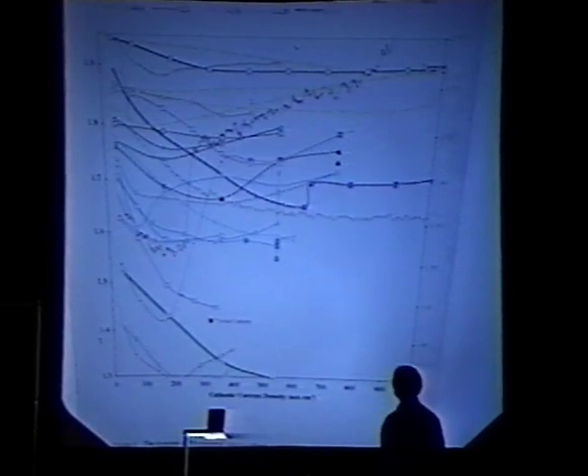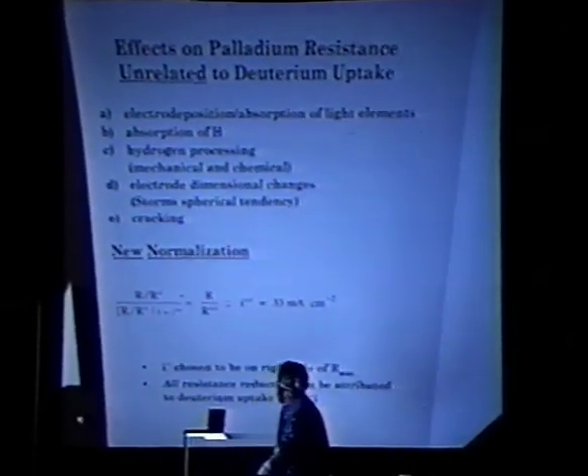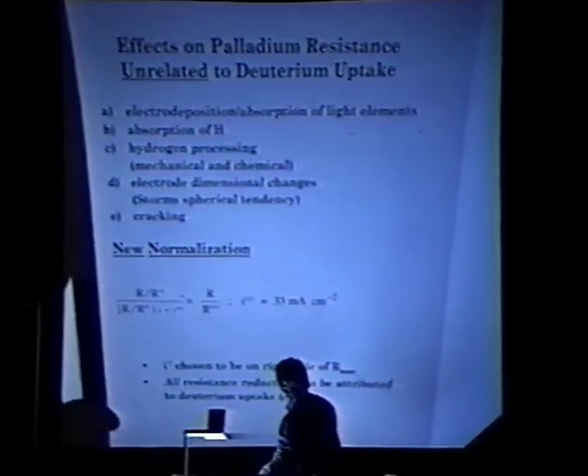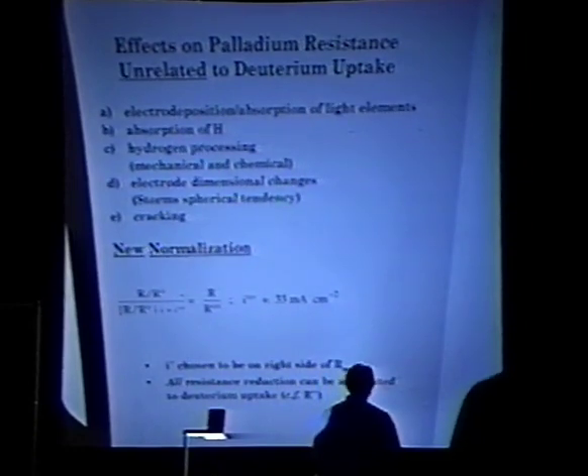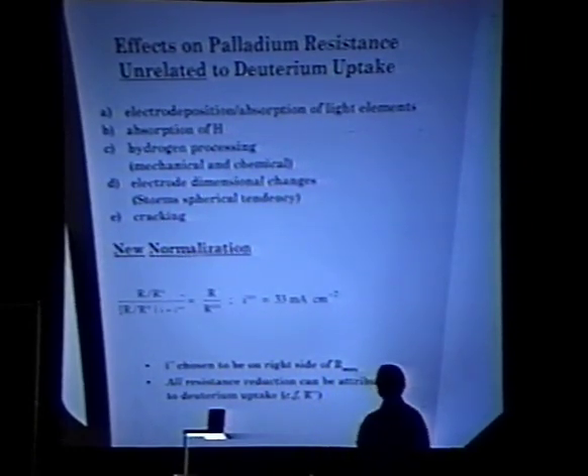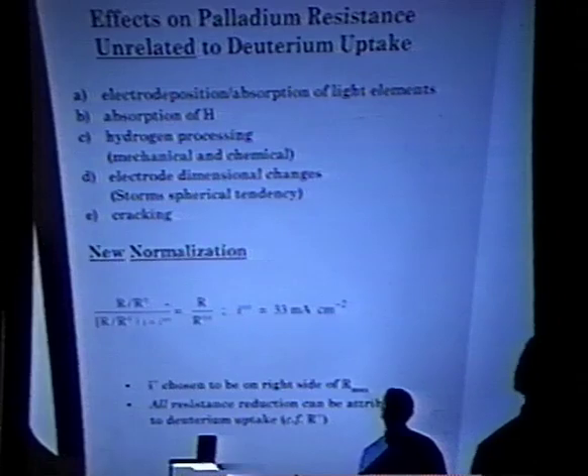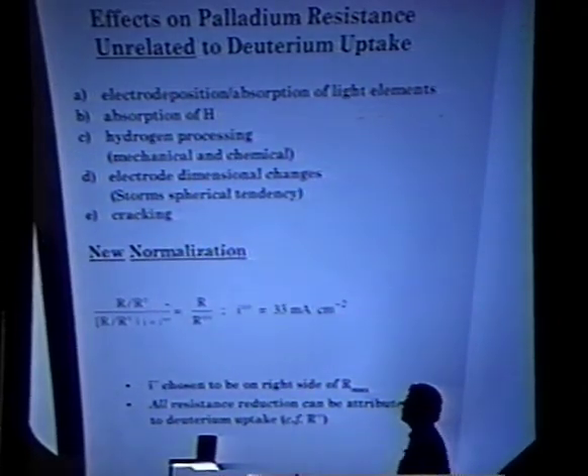There is a trend of a sort that the excess power tends to be observed at high current densities and towards low resistance ratio, as I suggested, but any sense of a mathematical predictive quantification of this effect, you certainly can't discover it by looking at those data. Why not? Well, we're measuring resistance ratio. The resistance ratio is affected by things other than the absorption of deuterium into the palladium lattice.